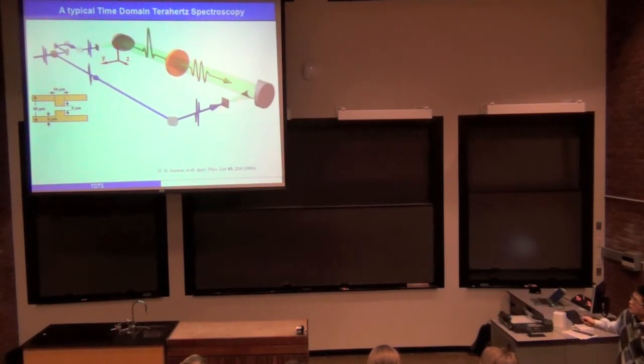It goes through our sample and then gets directed to the detector. And another pulse we split here would hit the detector at the same time. The lengths of those two pulses shown here are not to scale. The Terahertz pulse is usually a picosecond long, but this other pulse is usually a couple of tens or hundreds of femtoseconds. So if you think about it, this pulse is really much shorter than the Terahertz pulse. By changing the delay stage, we can tune when this pulse hits the detector. As a result, we can use this pulse to chop off this terahertz pulse or measure this terahertz pulse.